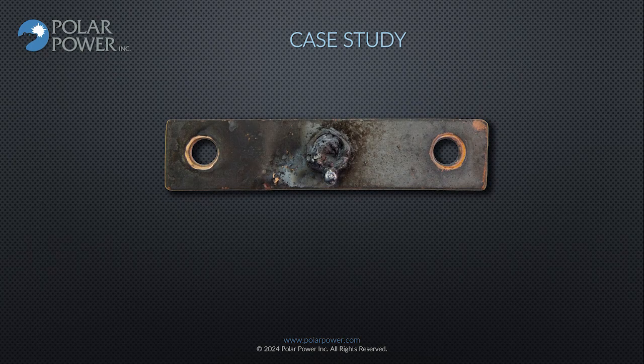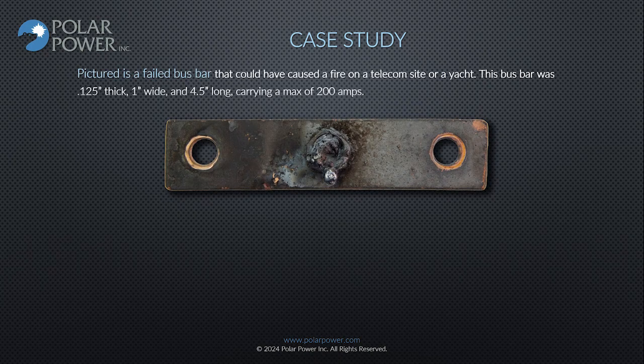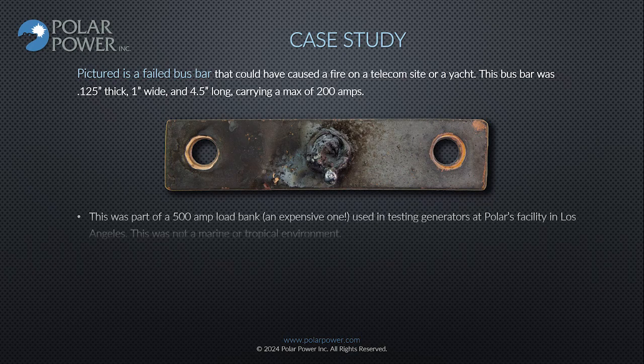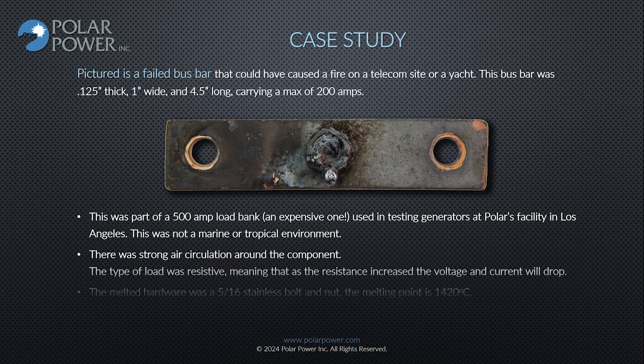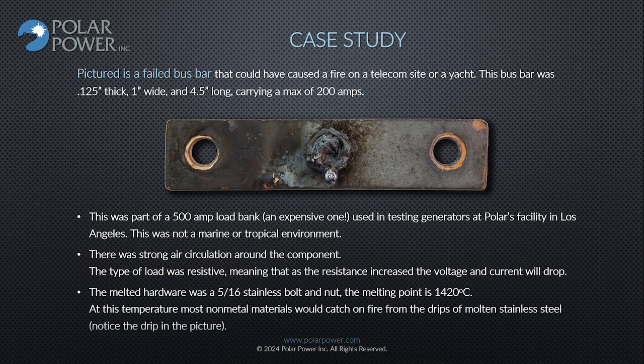And now, the case study. Pictured is a failed bus bar that could have caused a fire on a telecom site or a yacht. This bus bar was 1/8 of an inch thick, 1 inch wide, and 4.5 inches long, carrying a maximum of 200 amps. This was part of a 500 amp load bank, an expensive one, used in testing generators at Polar's facility in Los Angeles. This was not a marine or tropical environment.